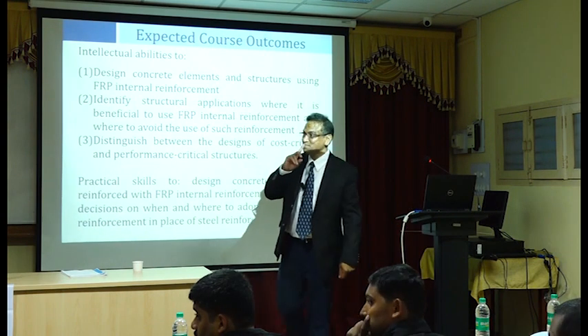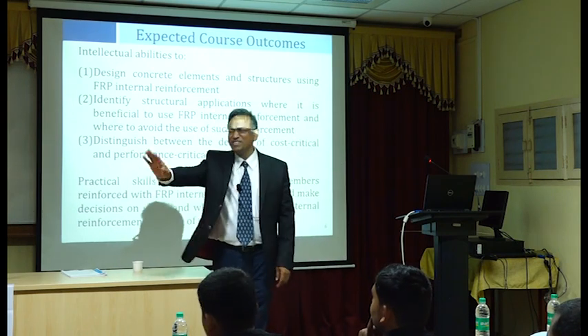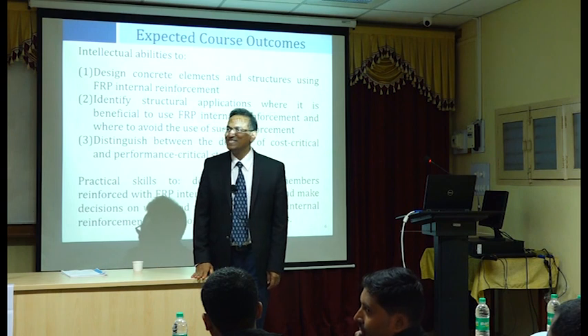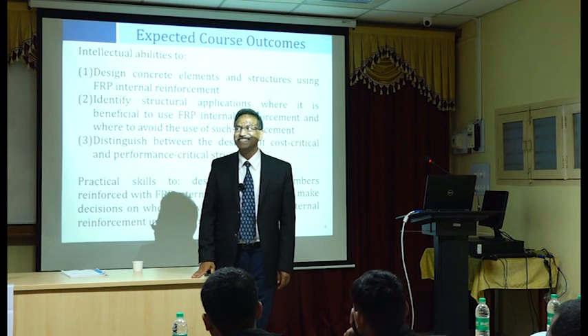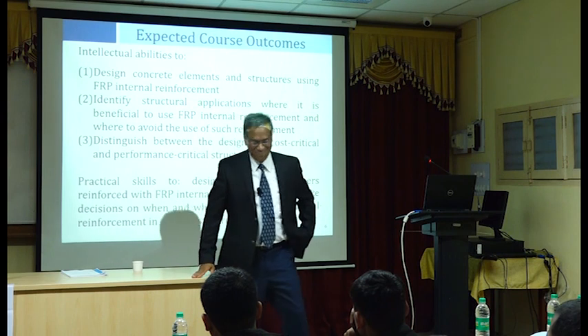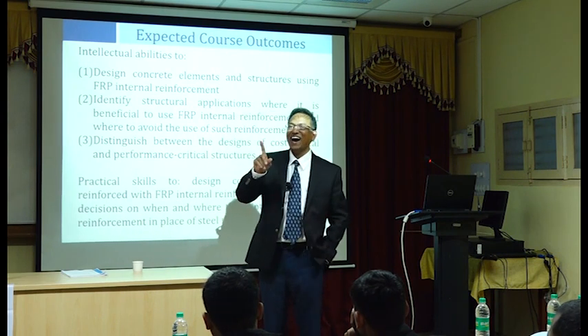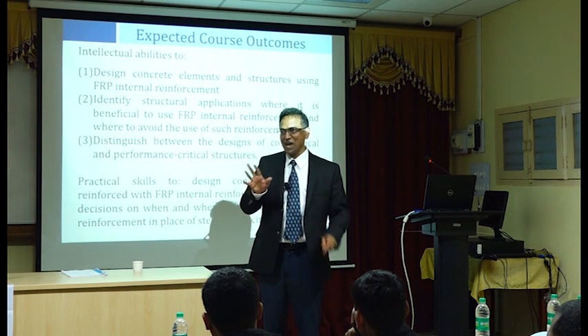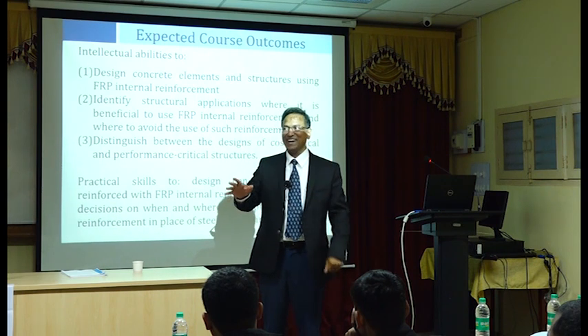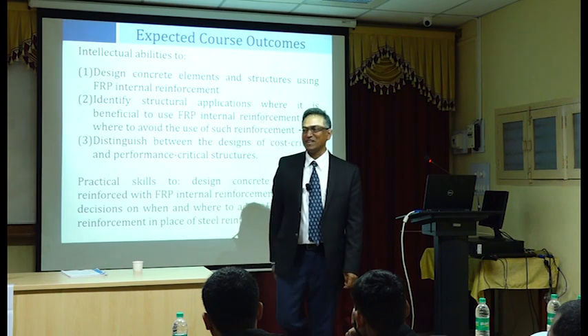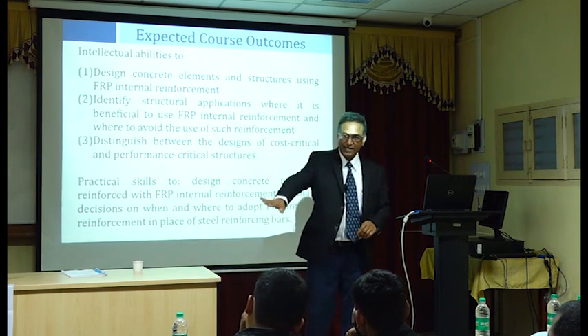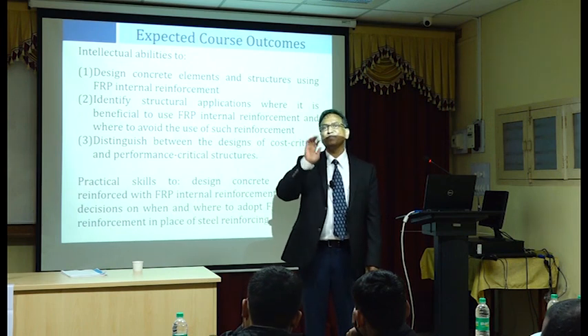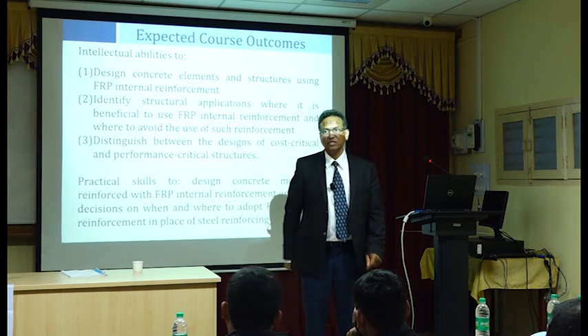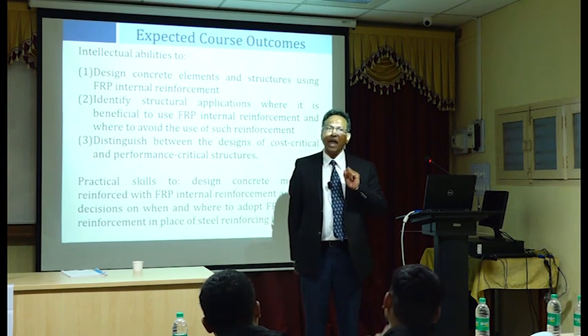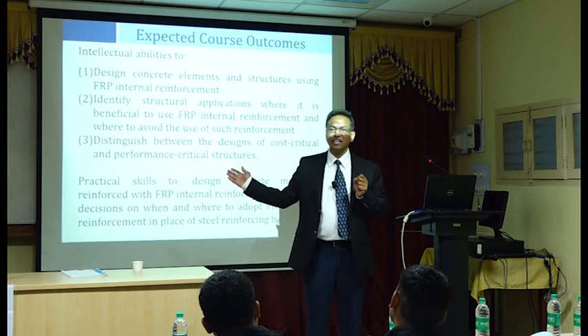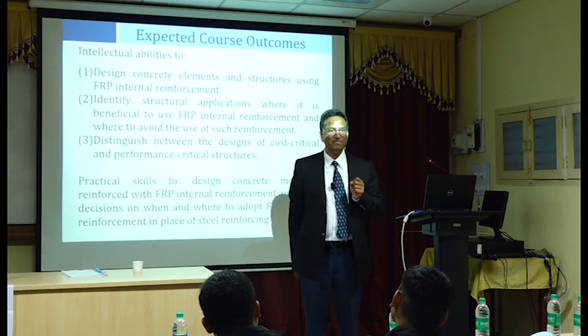The bonding between the reinforcement and the concrete. Absolutely. That is the reason why people are not recommending fully the epoxy coated bar. On Thursday, second session, I'm going to present some nice material on what the problems are with epoxy coated bars. There are many problems with epoxy coated bars. That aside, at site, what is the problem? The coating always gets damaged, okay? And if there is no proper inspection, nobody will know it. That's a big problem.